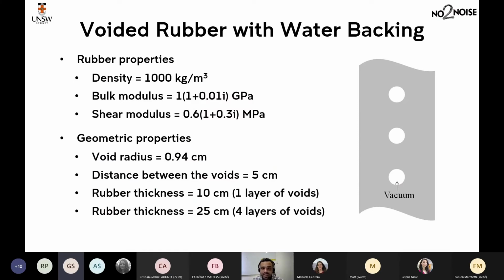So let's start with this simple rubber medium, and in that we have cavities. We have a layer of cavities. So in the direction of sound propagation, we have either one layer or four layers of cavities, right? And it's periodic. The density of rubber is very close to the density of water, which is 1000 kilograms per meter cubed. The bulk modulus and shear modulus values are given here. You can derive them using Young's modulus and Poisson's ratio.